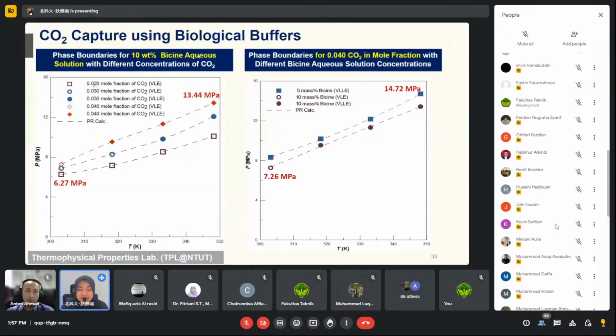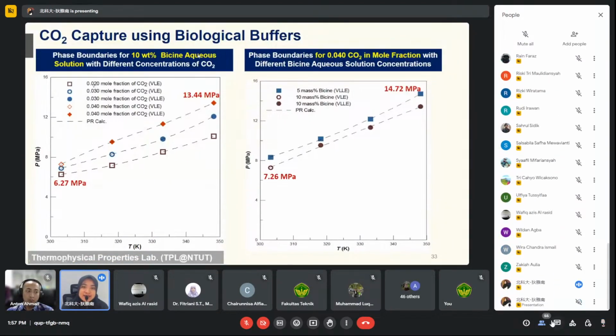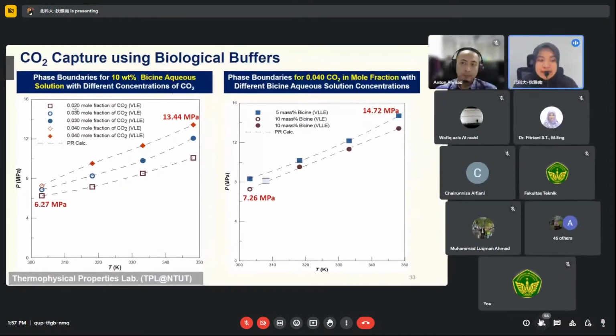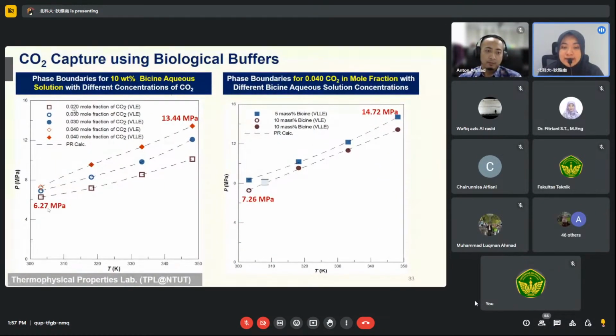Aqueous, it's water. It means ada air di dalam sistem tersebut, sehingga itu juga bisa hindered kemampuan dari solubility chemical tersebut. Nah, di sini kita bisa lihat we have 6.27 megapascal up to 13.44 megapascal. Jadi around 134 bar. Dan dia baru bisa capture sekitar 0.04. Nah, except this one. This one data is 3 data. It's about VLLE. So they have 3 phase. So it's not that good to capture the CO2.